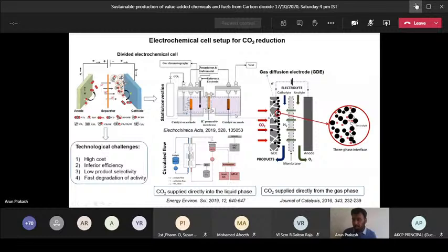For instance, you can observe for the potassium hydroxide. We all know potassium hydroxide is a strong alkali, right? The pH will be 13. So before bubbling it is around 14, but after bubbling it drops to 8. So you can imagine the pH change from 14 to 8. So almost it becomes half.